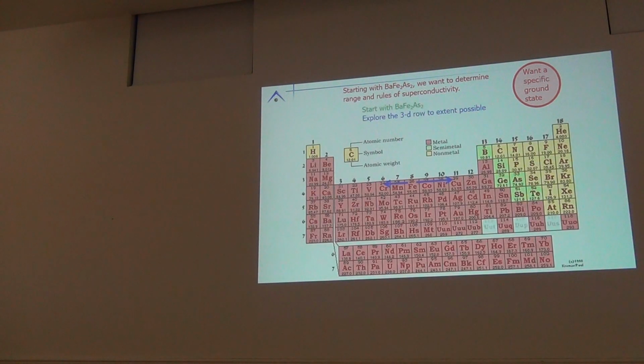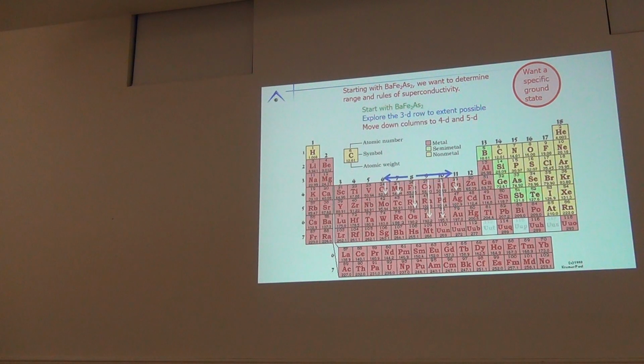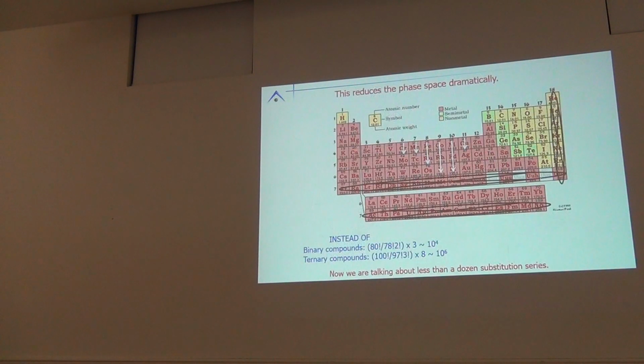Basically what that means is we could start with the barium iron 2 arsenic 2, and instead of iron, we could consider substituting in cobalt, nickel, copper, or manganese, chromium. We don't need to limit ourselves to the 3Ds. We can go down to 4Ds or even 5Ds. Now, that means instead of having millions of compounds, if I'm just doing things randomly, I now am talking about a dozen substitution series. So I'm just trying to show you how you limit phase space.